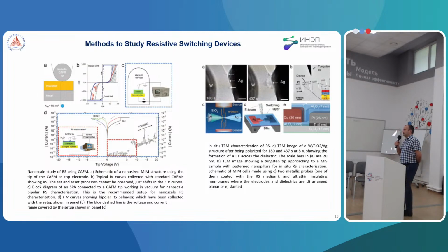for nanoscale characterization. This is a very good method to provide information and visualize resistive switching phenomena. On the right part of the slide, we present in situ TEM characterization, high-resolution TEM images of the switched structures, and we can see by TEM how the physical mechanism works in these materials.